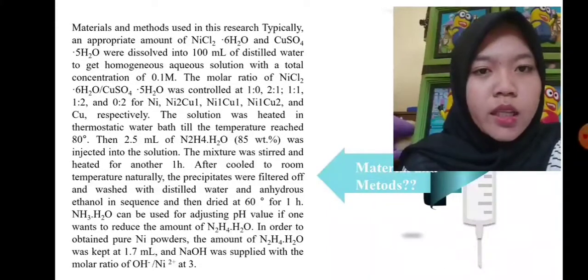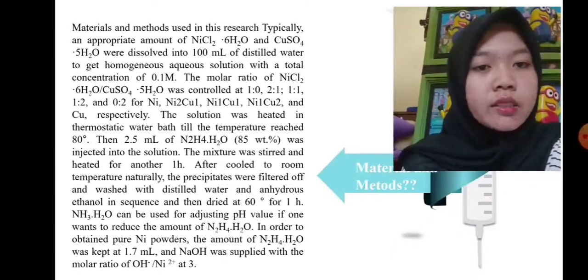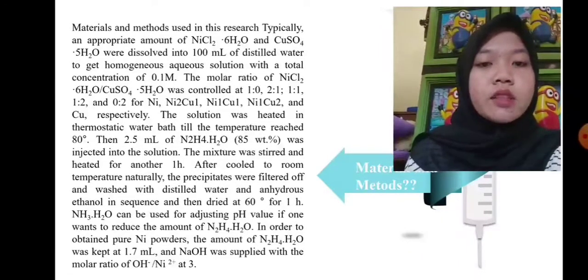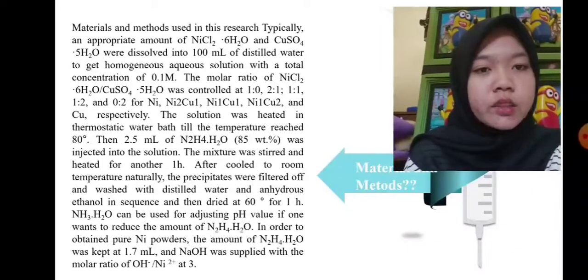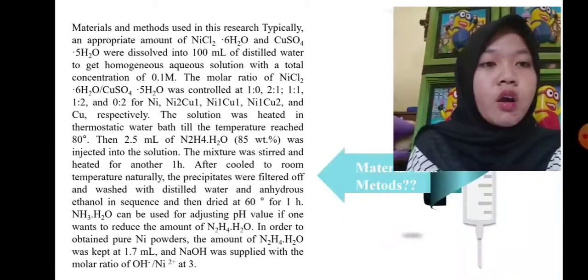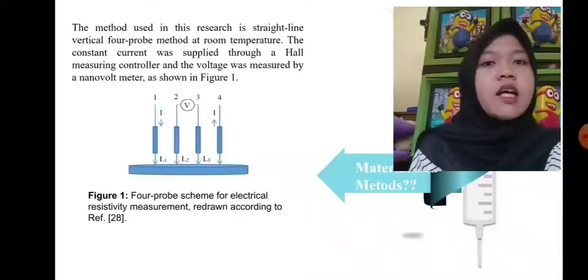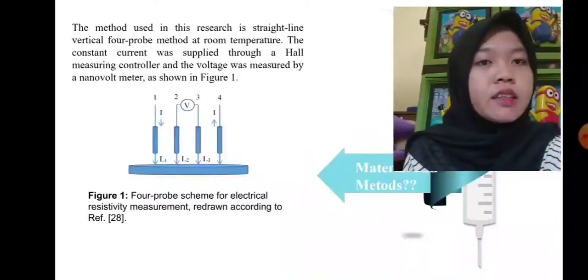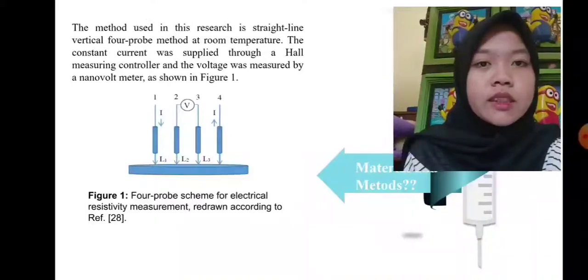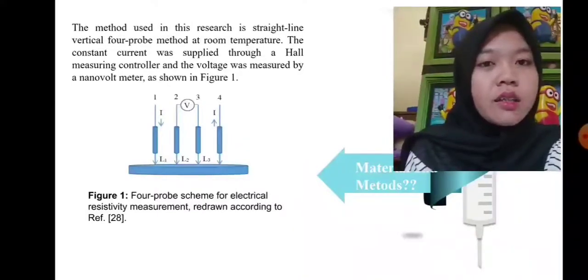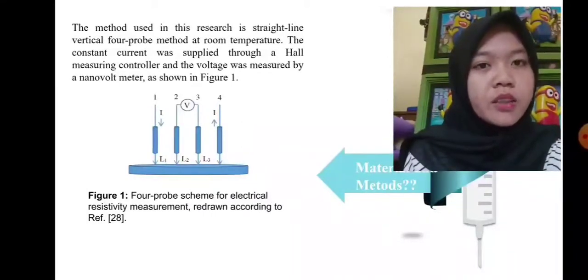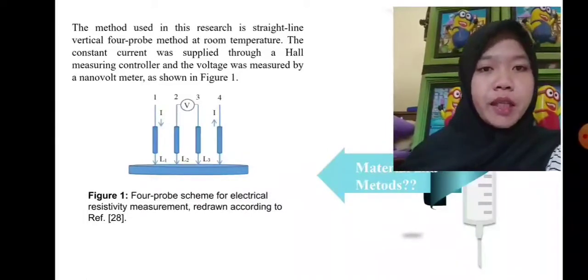If one wants to reduce the amount of N2H4 in order to obtain pure nickel powder, the amount of N2H4 was kept at 1.7 milliliter, and NaOH was supplied with the molar ratio of OH-/Ni2+ at 3. The method used in this research is the straight line vertical four probe method at room temperature. The constant current was supplied through a Hall measuring controller, and the voltage was measured by a nanovolt meter as shown in figure 1. You can see my PPT for figure 1.